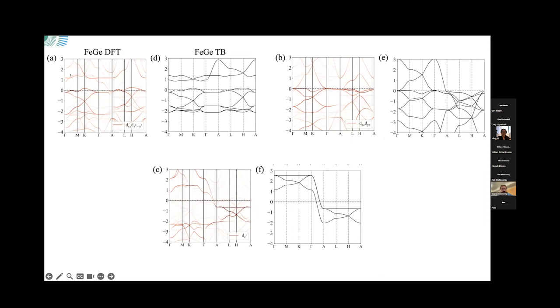Moreover, it gives you the flat band around energy 1, which is important in other compounds, some nickel compounds that we'll put out soon. Now you can also see, again, this is H2, that you have flat bands again below the Fermi level also. And these models, for example kagome, just the pure kagome principle, will not give you these flat bands. Okay, these two flat bands here.